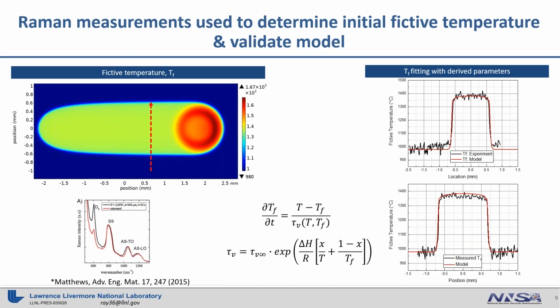So we have a model that can output the fictive temperature, great, but to inspire some confidence, we mapped it out and compared it against measured fictive temperature. So on the right-hand side, the red curves are the model that's predicted, and the black curves are fictive temperature measured by Raman spectroscopy. And so those agree well. And there's those equations that I referred to on the prior slide for those of you that just like to get into the math a little bit.